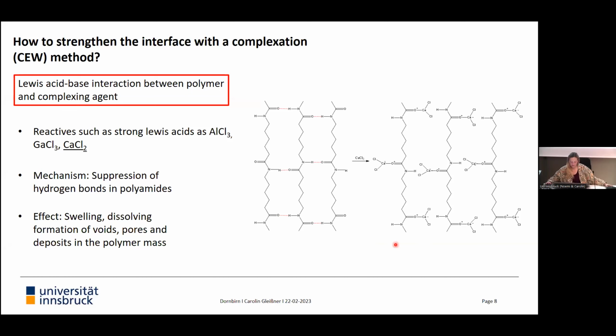And if you do this treatment, chains will dissolve. And also if, for instance, water molecules can penetrate between the chains, then swelling can also occur. And as an effect, you have, like I said, a swelling and a dissolving of the polymer. And also, if you wash everything with water, you can do a recomplexation, and these hydrogen bonds will reform, but since some polymer chains dissolved, you get a polymer that has more voids, more pores, you have deposits in the polymer mass, and you really get a rough surface.